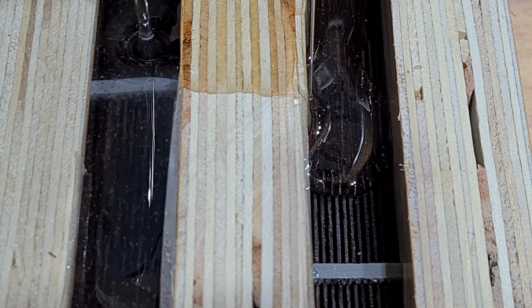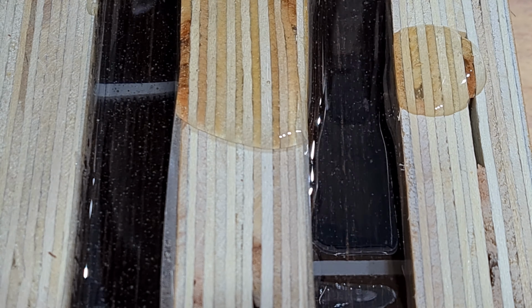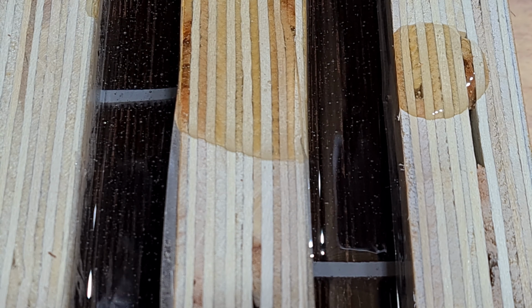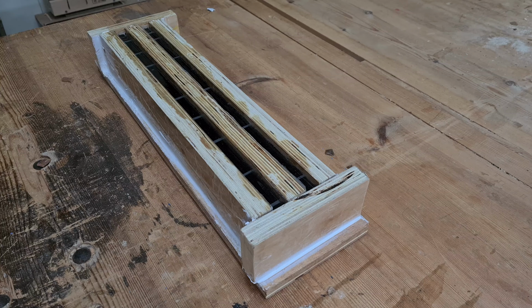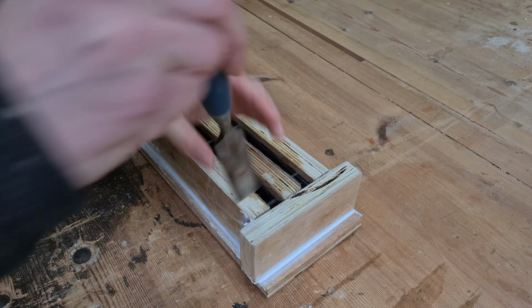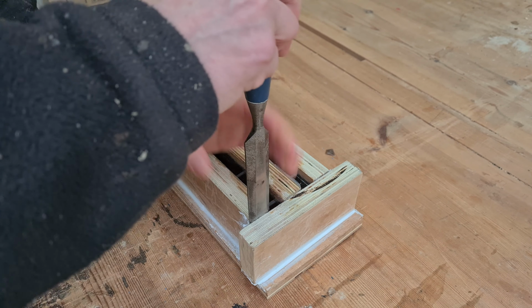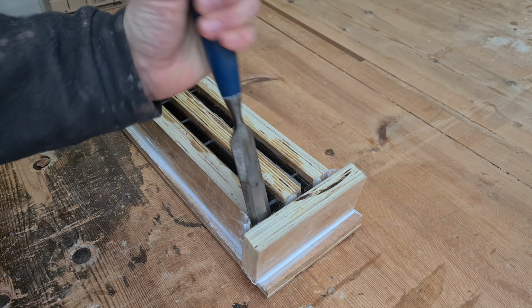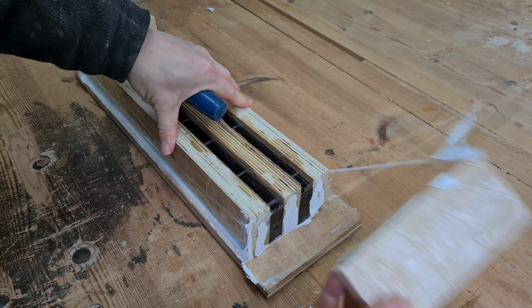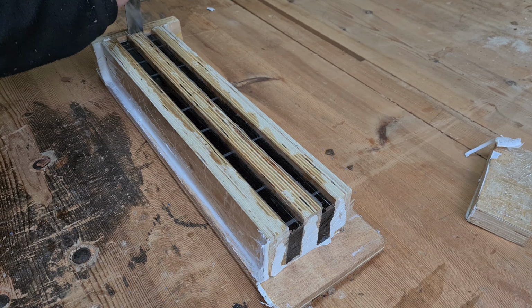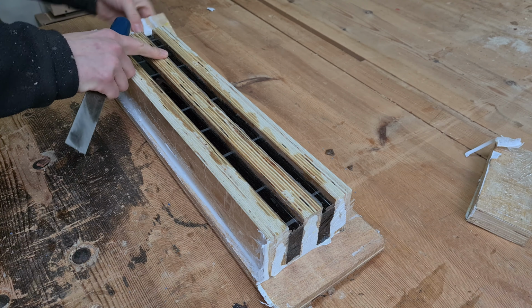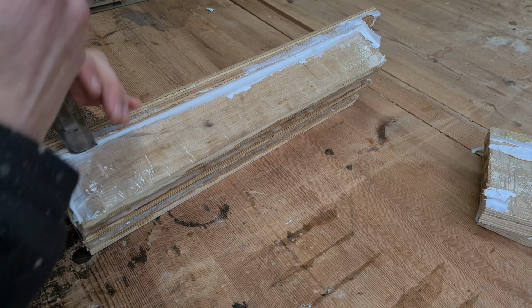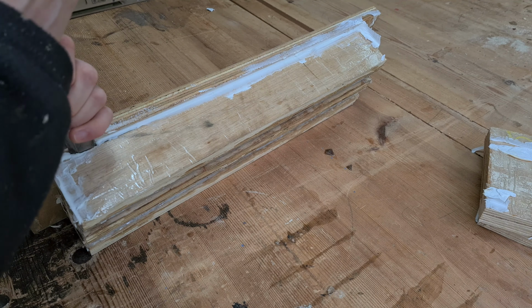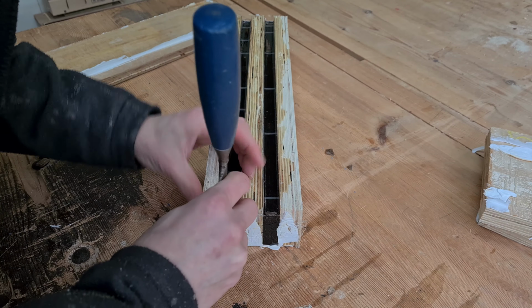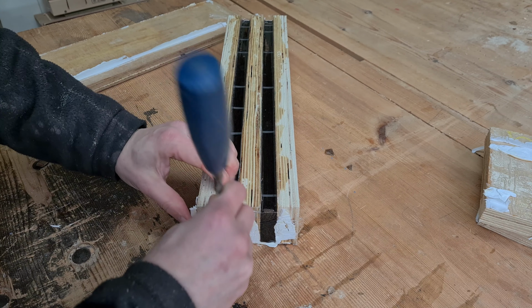The positive feeling I had about this new methodology lasted approximately 5 minutes after I'd poured the resin, as I realized that I'd used the wrong type. It was a shallow rather than deep pour. And it's not always a problem, except the walls of this veneer were very thin and allowed the system to heat up and thicken, which trapped a lot of tiny air bubbles. Now, I tried to pour as much of it away as I could and then replace it with deep pour, but some of the bubbles remained and a few layers had collapsed and stuck together because of the viscosity of the shallow pour resin.